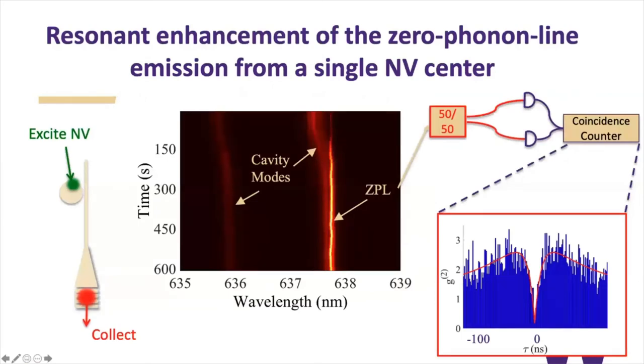And here is an example of the actual experiment where you can excite a single nitrogen vacancy center. You always have to show that it's a single one by, for example, doing a G2 measurement, which I show here. You can tune the cavity onto resonance, which means that the cavity round trip for light at the wavelength constructively interferes, and that happens at the same transition as that defect. So here we're tuning that transition onto the defect transition, and then suddenly we get light from that single quantum defect to efficiently couple into this waveguide, and we can collect it somewhere else on the chip after routing it.